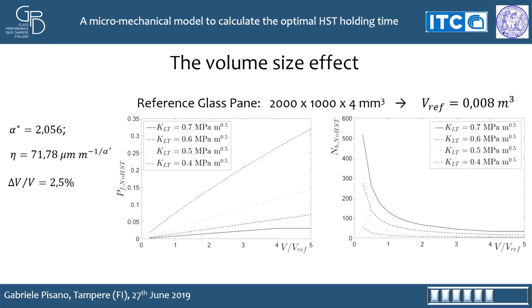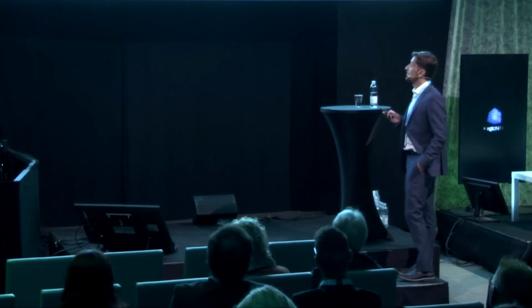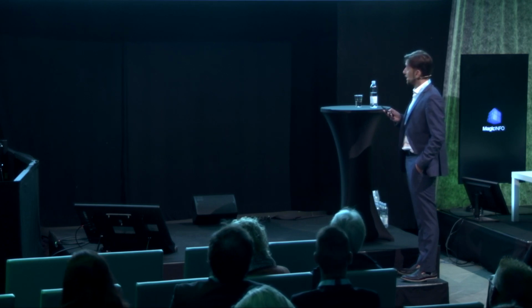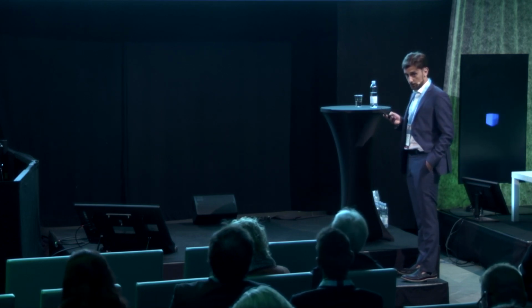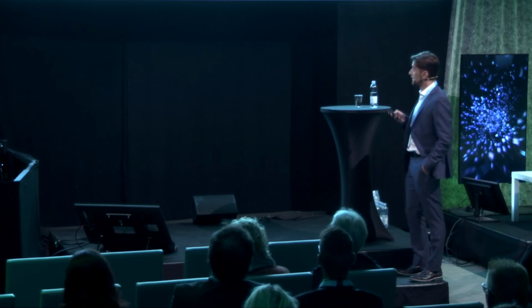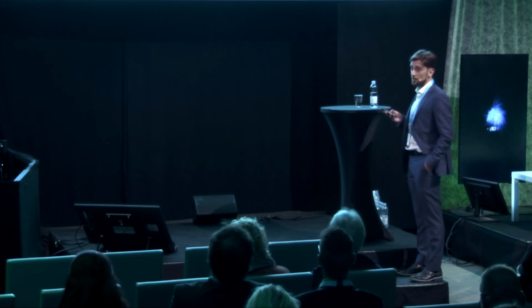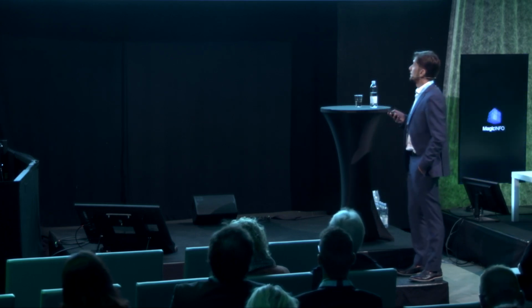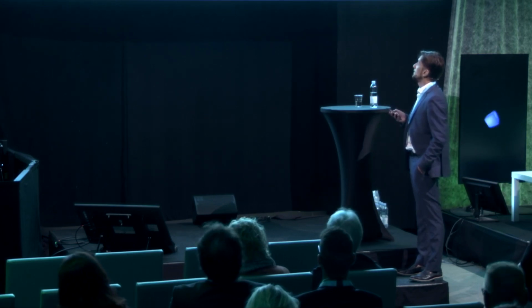Here I have defined a reference glass pane, 2 meters per 1 meter per 4 millimeters, and I plotted the probability of failure for elements that are not subject to heat-soak test, how it varies with the ratio between the volume and the reference volume. Here it is evident that the model is strongly affected by the value of the stress intensity factor to be considered critical for rupture in the long term, and this depends upon the subcritical crack growth, obviously. But then we come back to this point.